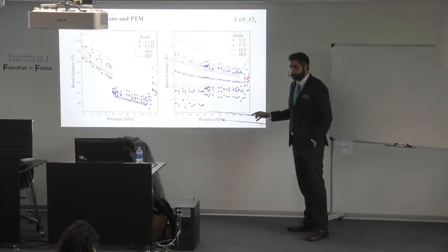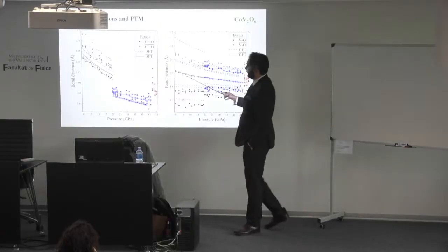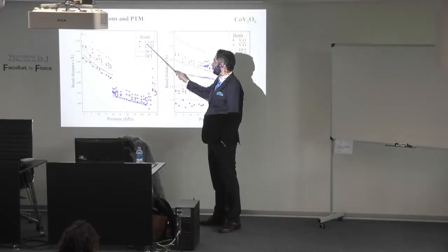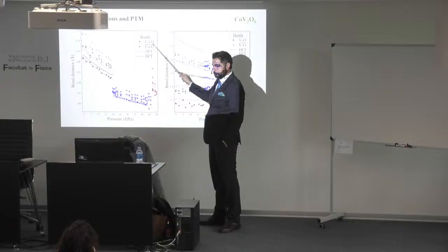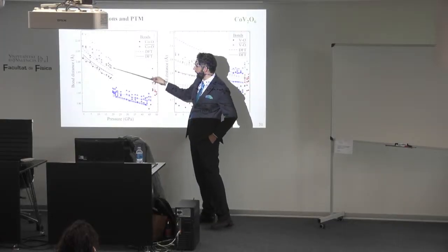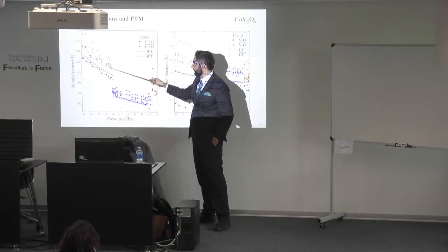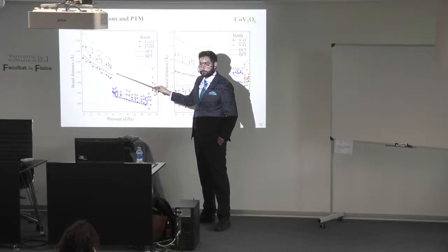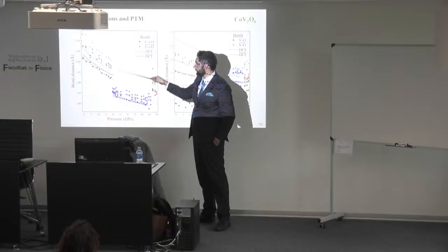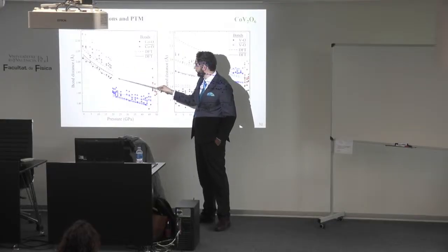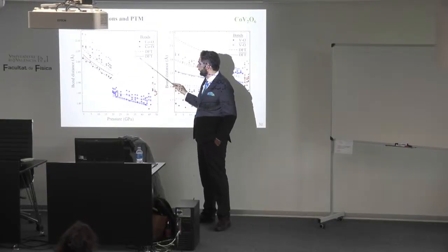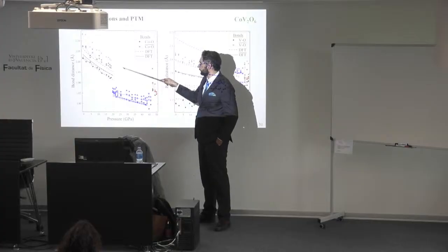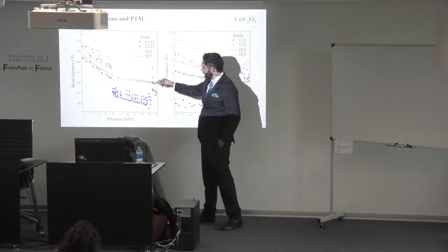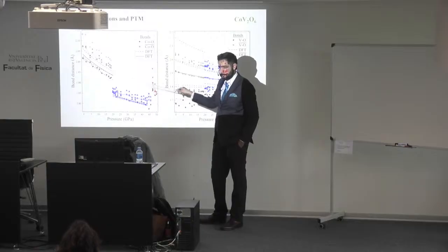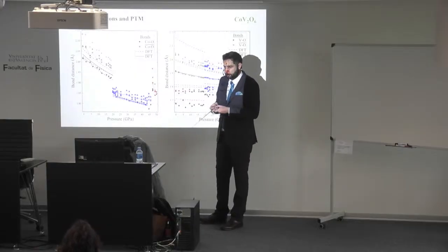So getting into the detail, these are the bond distances between the cobalt and the oxygens. Okay, we have 3 different ones. The average one is the one empty, and the lines are calculations. Okay, so we see that they are in agreement. And for the cobalt octahedra, it shrinks after the phase transition. It jumps. All the bonds got shortened.